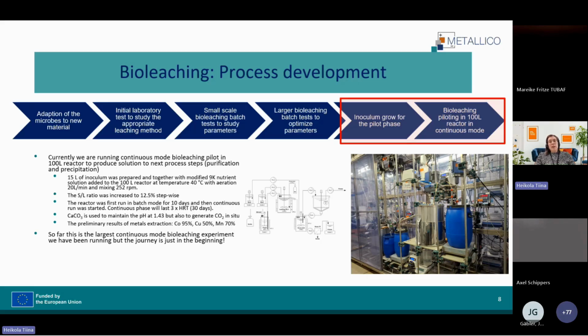And at the ramp-up phase, the solid-liquid ratio of the reactor was increased stepwise in 4 batches to 12.5%. And after the target SL ratio was achieved, the reactor was run in batch mode for 10 days, and then the continuous run was started. That will last 3 times HRT, so the total time will be 30 days.